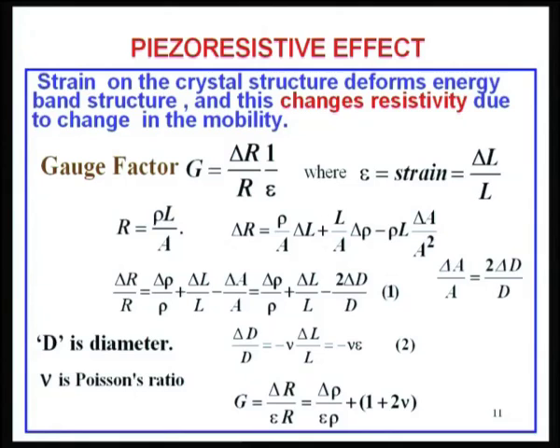Okay. So, delta R takes place due to change in rho, L and A. Okay. So, delta R can be written in terms of all these changes as rho by A into delta L, plus L by A into delta rho, plus rho into L into differential of 1 by A, that is minus delta A by A squared. Now, there is one term one has to remember, delta L by L is actually the strain epsilon. Delta A by A is the change in the transverse direction, and that you can put in terms of the diameter as twice delta d by d.